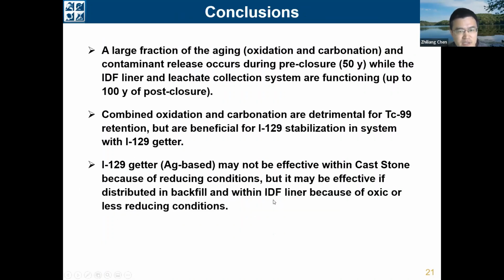Yeah, and finally, we have some takeaway messages here. A large fraction of the aging, including the oxidation and carbonation, and contaminant release occurs during the pre-closure period, a relatively short period of time of 50 years. And during this period of time, the IDF liner and the leachate collection system are functional. And also the combined oxidation and carbonation are detrimental for technetium retention, but are beneficial for iodine stabilization in the system with getter. And finally, the getter may not be effective within the Cast Stone because of the reducing conditions there, but it may be effective if it's distributed in the backfill or in the IDF liner because of the oxic or less reducing conditions there.